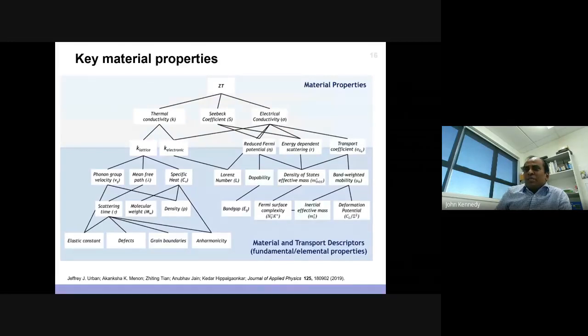But the other two factors are still possible because they are semiconductor driven: the Seebeck coefficient and electrical conductivity. In terms of the band diagram, for the Seebeck coefficient you have the reduced Fermi potential, and depend on the scattering that happens in the energy level, and also the transport coefficients. Then, in our solid state physics Kittel context, you look at the density of states, and maybe the effective mass of the particular element needs to be tuned. And then the mobility comes in, because when you add too many electrons, the other things change as well.